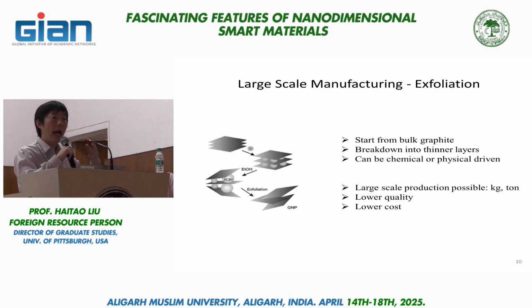This is the case where you don't do anything special, you just add the bulk layered material in the solvent, just apply mechanical disruption. If that disruption is strong enough, if you pick the solvent combination the right way, or if you add some additive, oftentimes surfactants, if everything works out, you will just exfoliate into single sheets, magically. Okay. All right, so this is the least disruption to the lattice, and probably the lowest cost as well.